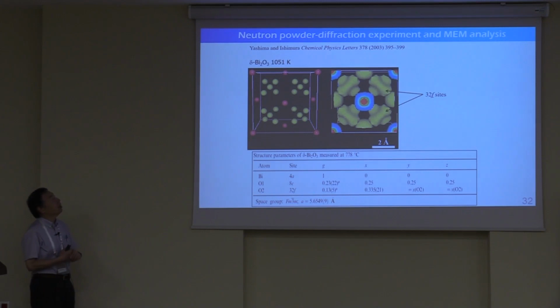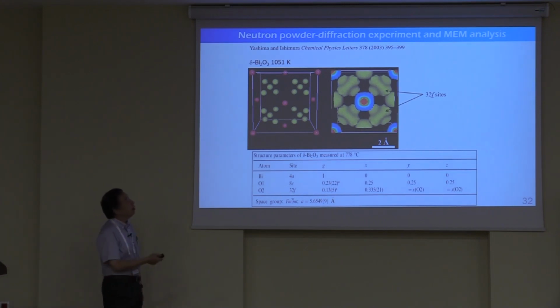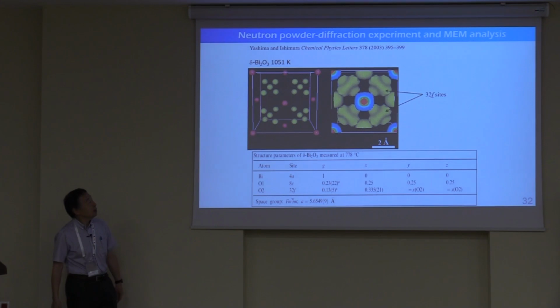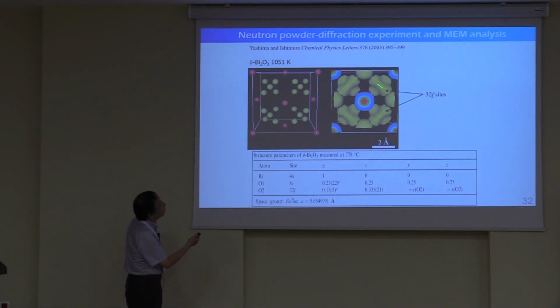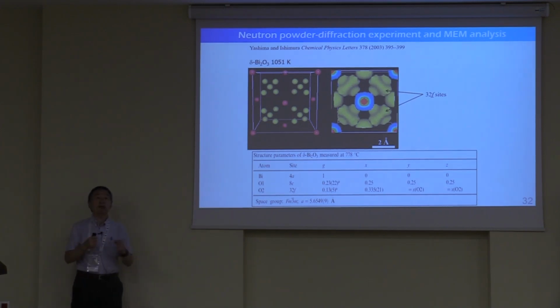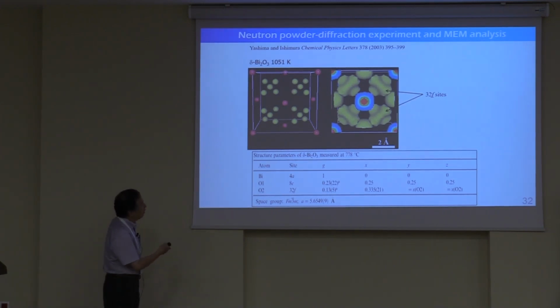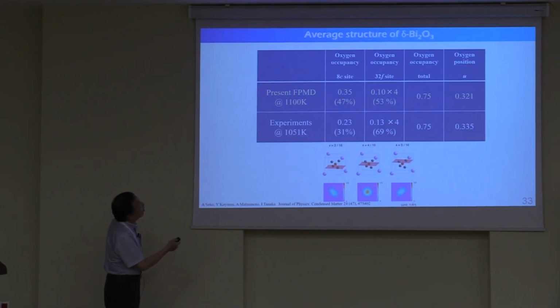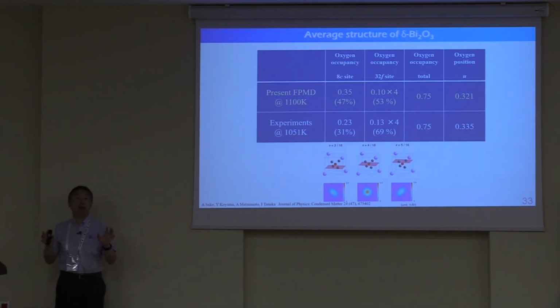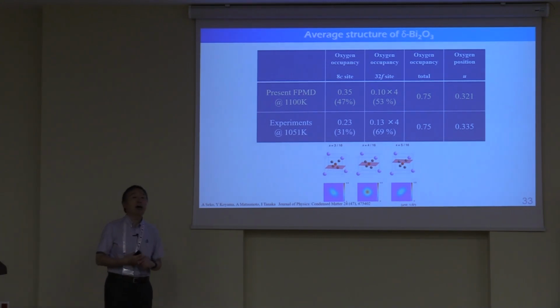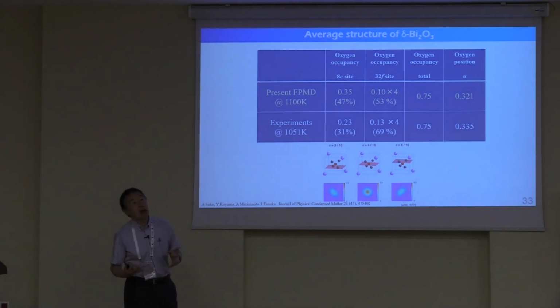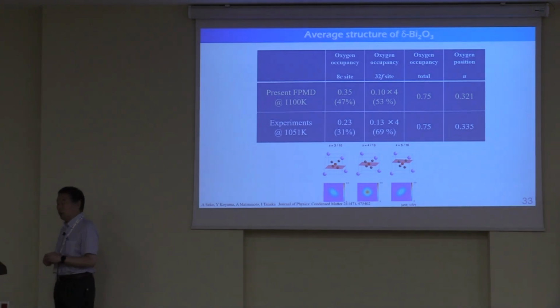The experimenters did a very detailed neutron powder diffraction experiment and a very detailed maximum entropy method analysis to find that the oxygen is actually moving toward this 32f site. So they analyzed the result and also the oxygen density for the other site and the central site, etc. And the agreement with the experiment is very good. So in that way, the atomic movement, which is very important at high temperature, that type of information can also be obtained by first-principles calculation.